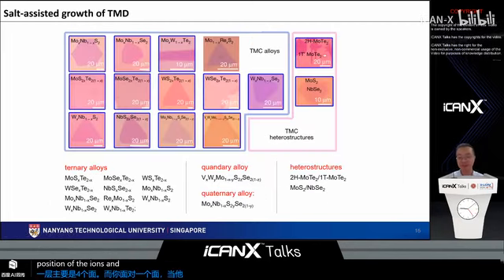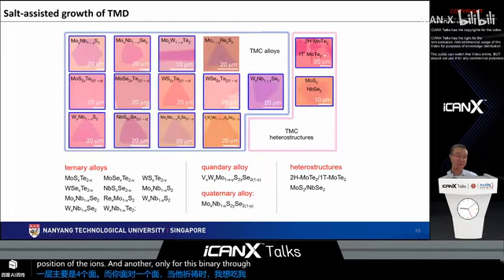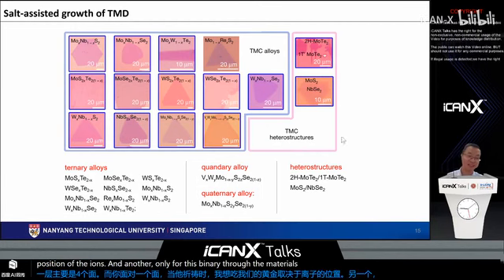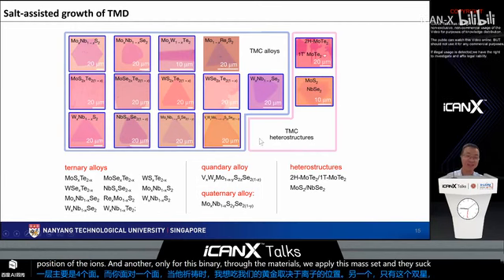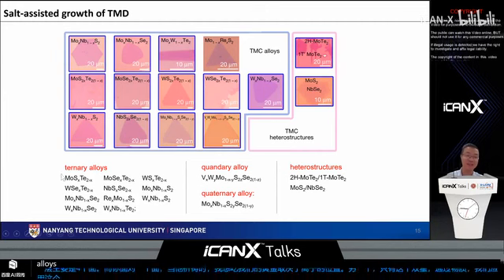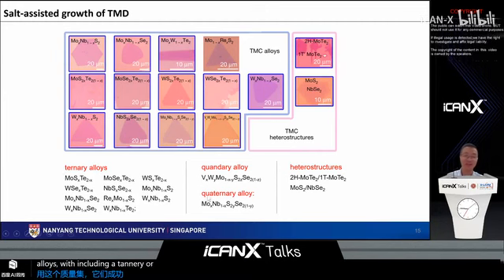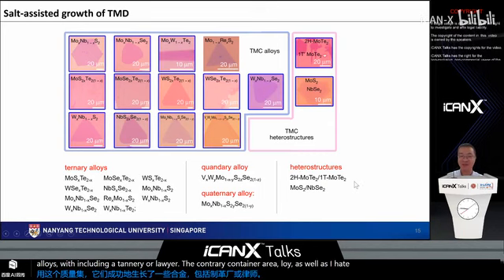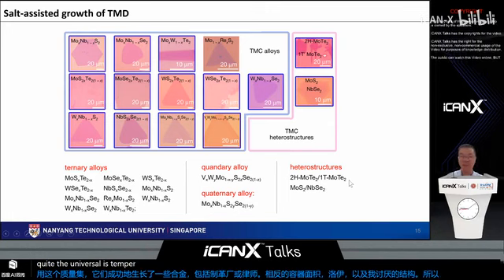And not only for these binary 2D materials, we applied this method and successfully grew some alloys, including the ternary alloy, the quaternary alloy, as well as heterostructures, which shows this method is quite universal. It can produce almost unlimited candidates of the 2D TMDs.